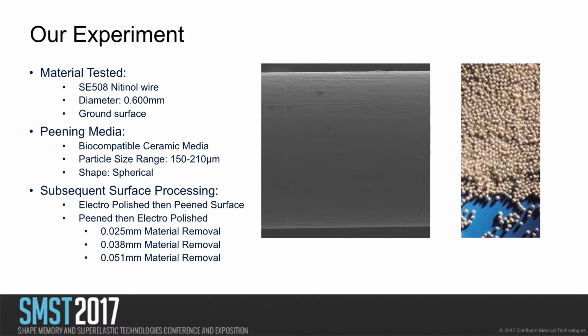And so what we did to test this is we started at the baseline. We looked at Nitinol wire, SE508 Nitinol wire with a diameter of 0.6 millimeters and a ground surface. This is an SEM image to the right here of that wire's surface. And for peening media, we chose a biocompatible ceramic media with particle size ranging from 150 to 210 microns that's spherical in shape.